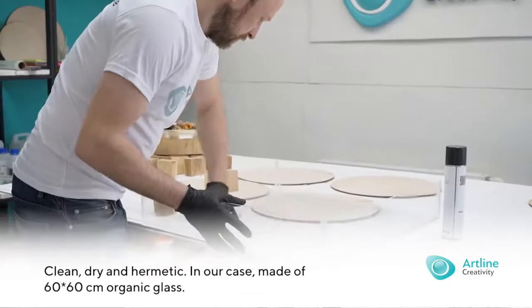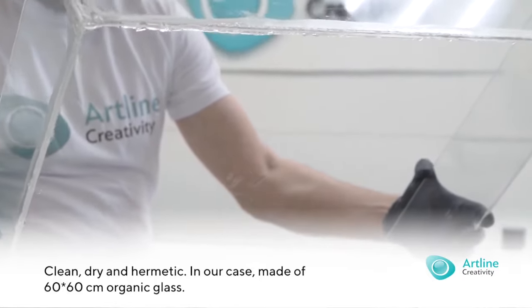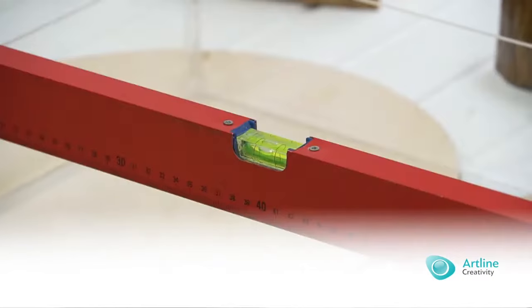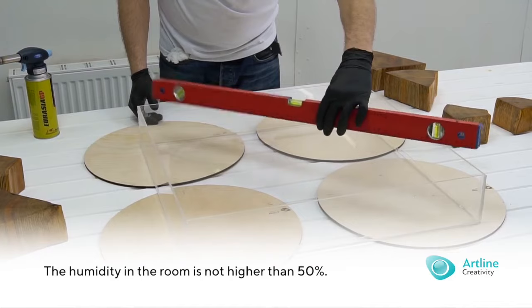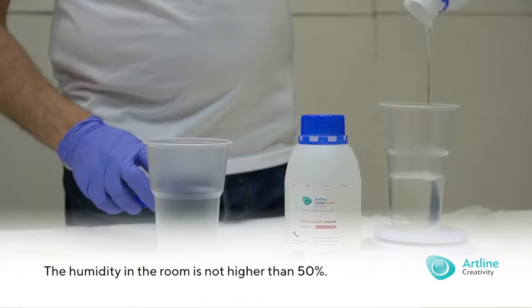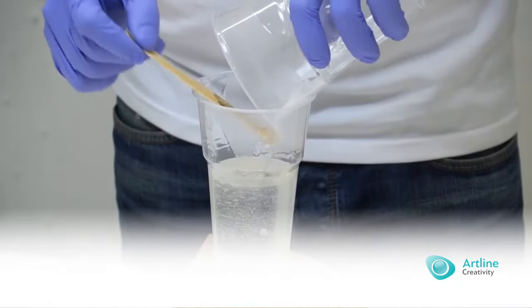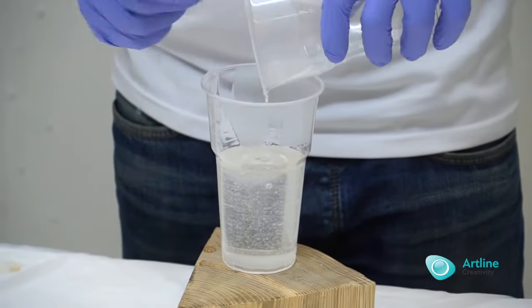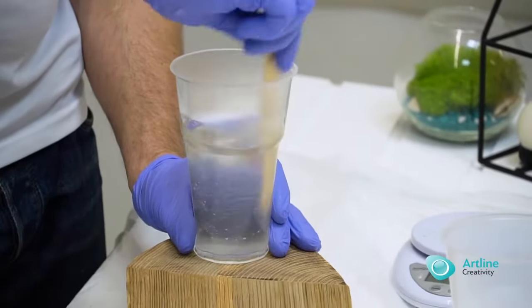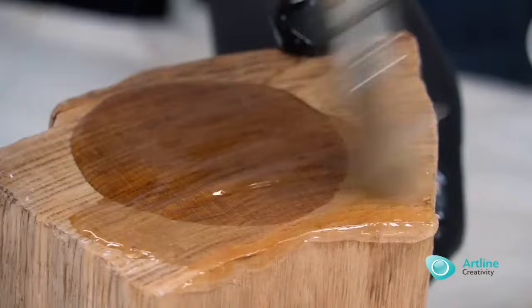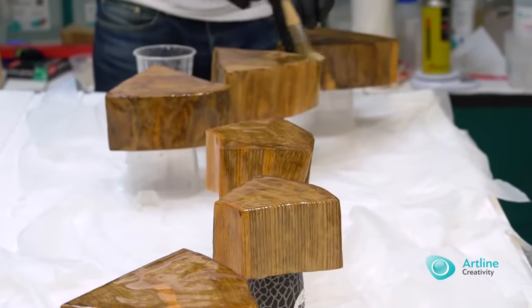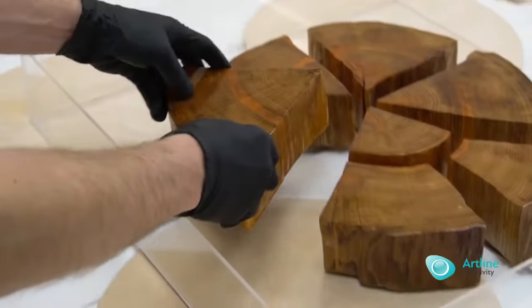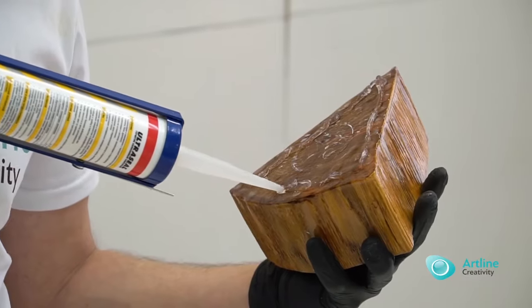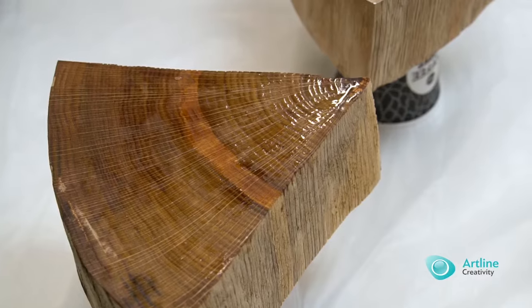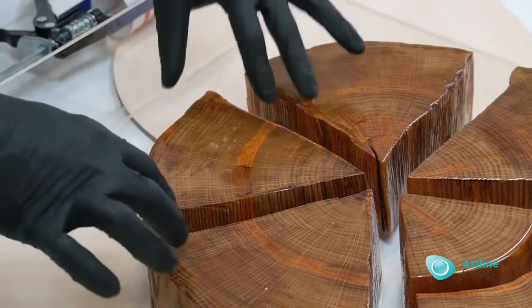The corners and places of connection were processed with transparent silicone sealants, checked for tightness with water. Filling: a pure, dry slice of oak with good adhesion to the resin. We covered it with Artline's epoxy resin because it polymerizes quickly, and 2 hours later we started casting. The primed parts of the slice were beautifully laid out on the formwork. They were glued to the bottom with a sealant, because without it, the resin would lift them to the surface.